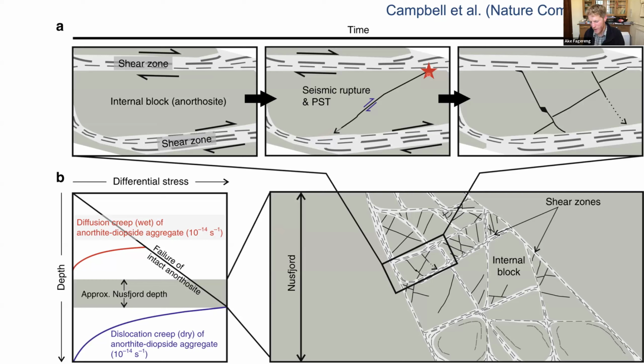But the seismic ruptures shown by the presence of pseudotachylite come from what we think is the deformation of these blocks, because if you're deforming these shear zones that are not parallel, you need to somehow deform these blocks at some point, at least to a small extent. So, dominantly what these shear zones have is a network of viscous flow around stronger blocks. And these stronger blocks locally need to deform at least a little bit by shear. And that's when you get pseudotachylites.